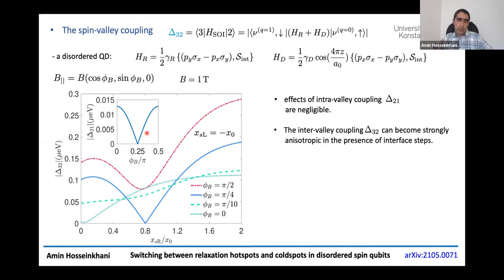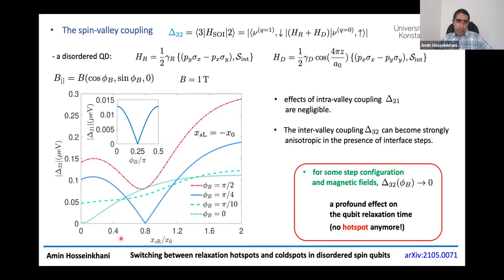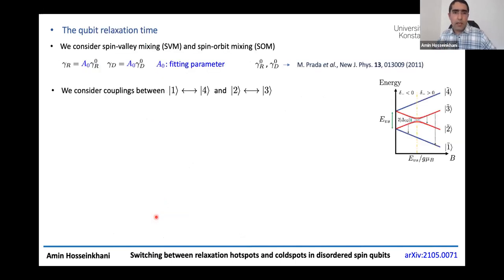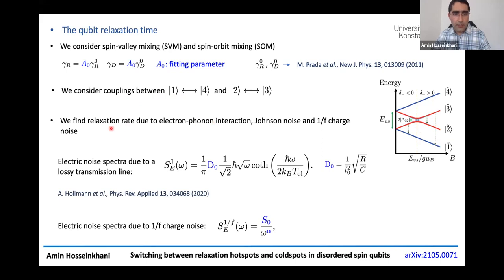There are two important highlights: first, because of the interface steps, the spin-valley coupling is strongly anisotropic. Second, at some specific field directions and step configurations, the spin-valley coupling actually vanishes. Now we analyze the qubit relaxation time: we define strengths for the spin-orbit interaction with a fitting parameter, consider couplings between states one and four and two and three, and calculate the relaxation rate through electron-phonon interaction, Johnson noise, and 1/f noise.